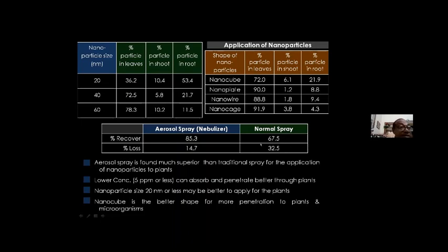Again, a particle size of 20 nanometers or less is best for agriculture use. You can see the results. When we are using a 20 nanometer nanoparticle, within 48 hours of spraying on leaves, we are getting 53% nanoparticle in the root. So they travel so much. But with 40 nanometers, we get only 21% in the root, and with 60 nanometers, 11%. So a smaller size nanoparticle is best for agricultural use. Again, cube shape nanoparticle is best for agricultural use compared to plate shape, wire shape, and cage shape. Within 24 hours, you find that 21% travel to the root, whereas nanoplate 8%, wire shape 9%, cage shape 4% only.